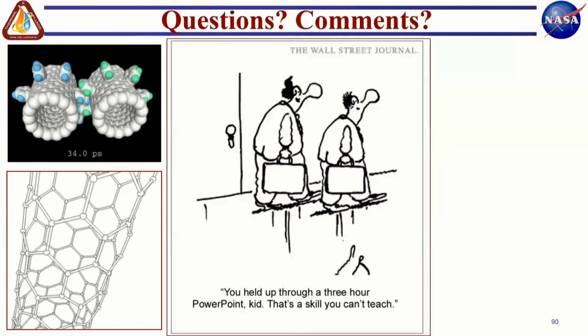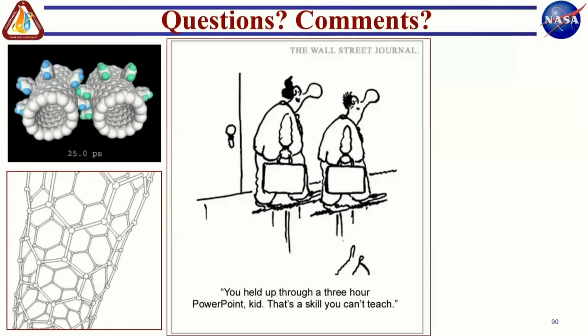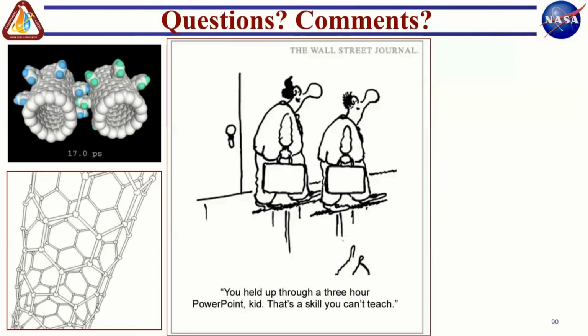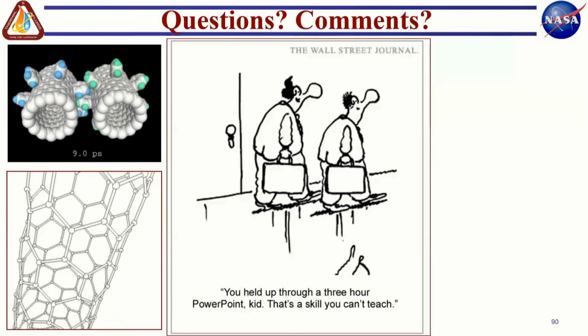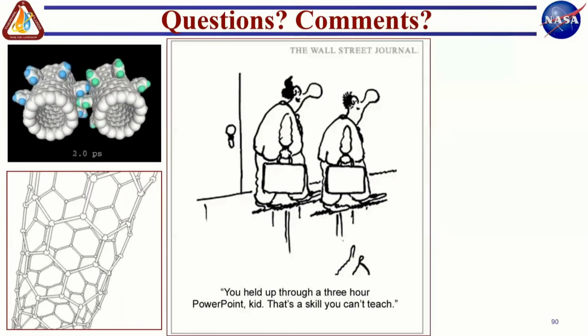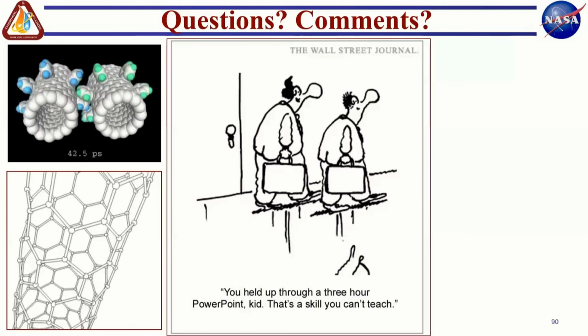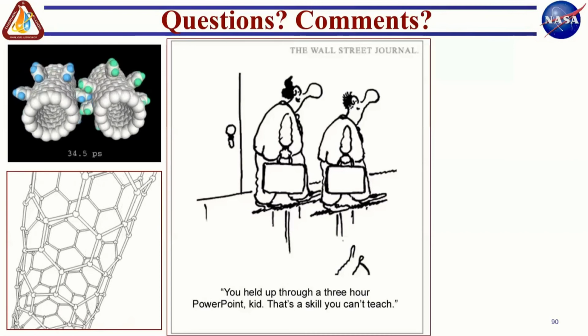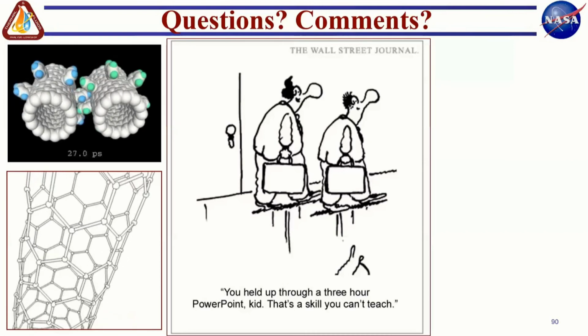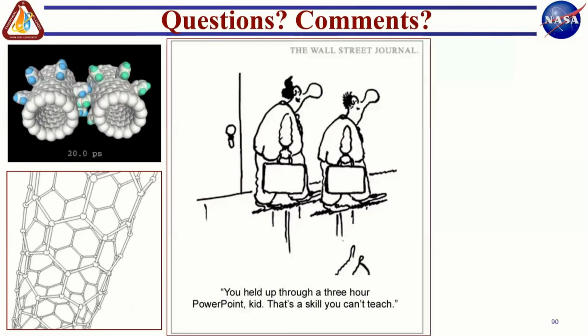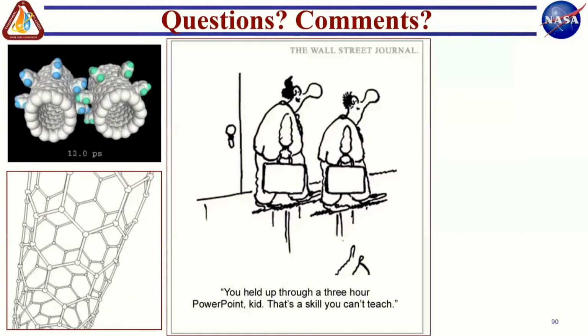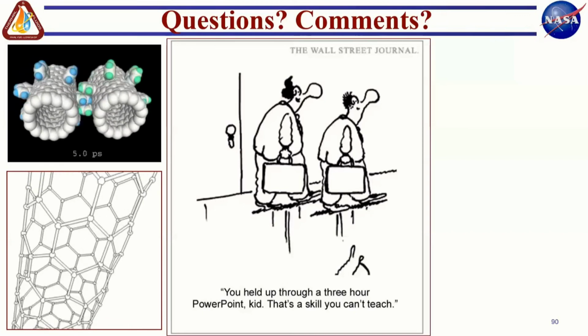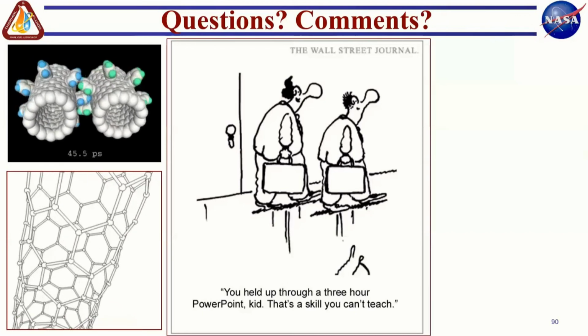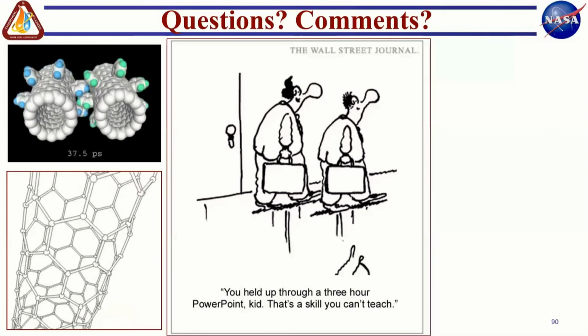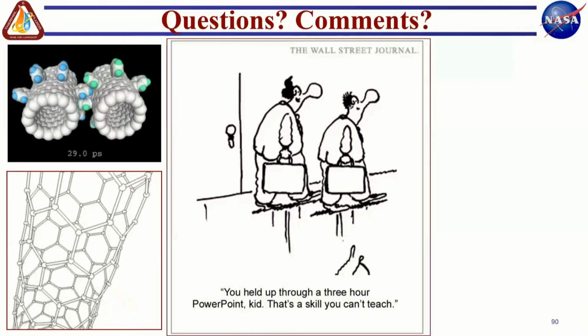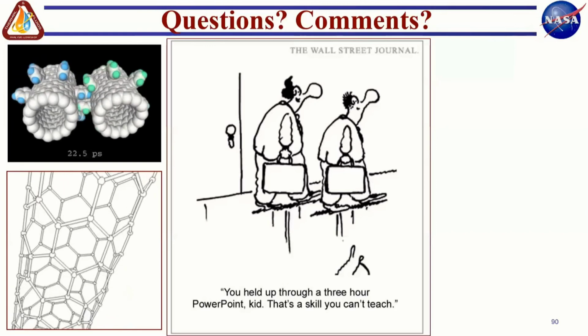So the fundamental problem there is small variations in the synthesis protocol can give you very different material properties. So the same ingredients, depending on the order in which you cook, is going to give you different flavors. So one has to pay a very close attention to the synthesis and almost have military discipline in making sure that every batch that you make, there was no variation in the synthesis protocol. Because one of the things we found was even simple changes in the synthesis protocol, you can end up with nanofluids with vastly different properties. So the stability of the nanofluids is very important.